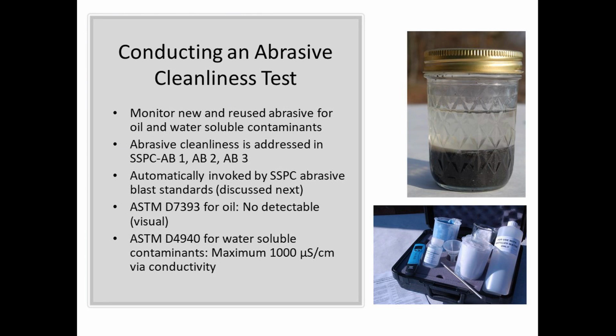The next automatic or indirect requirement, automatic communicates a little bit better, is making sure that our abrasive is clean. Whether it's new abrasive or whether we are reusing an abrasive like steel grit or steel shot, again, the SSPC cleanliness standards for abrasive blast cleaning require the abrasive to be verified for cleanliness. They require that clean abrasive be used. How do we determine that? What do we mean by clean? Well, there's two tests. The first test is the top one. We're checking for oil contamination on the abrasive by taking a sample of the abrasive and combining it with regular old tap water, shaking it up for about a minute, letting it settle, and then looking for an oil slick on top of the water. Very simple test to do, and it's very routine.